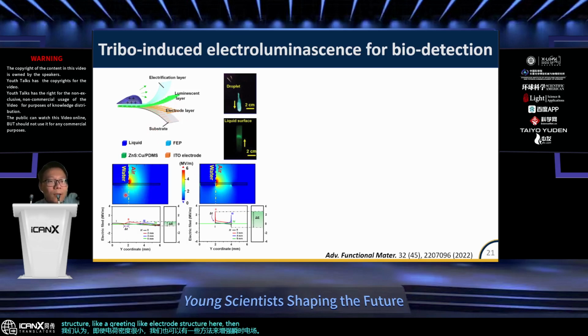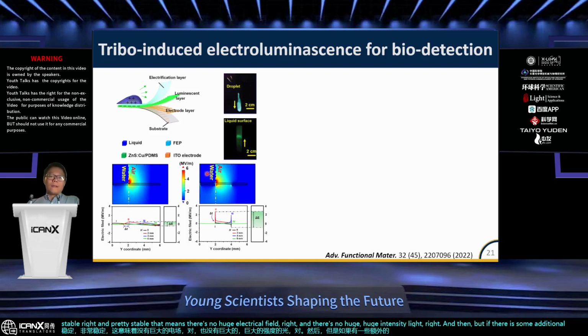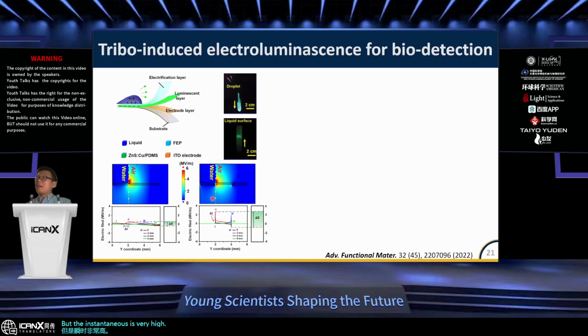Then we did some simulation. As you can see, when there are no grating electrodes, the electrical field change is actually pretty stable. And pretty stable means there's no huge electrical field, so there's no huge intensity light. But if there are some additional electrodes at the interface, when the water passes through the interface between the region with electrodes and the region without electrodes, the instantaneous electrical field becomes very high. And with this instantaneously high electrical field, we can actually generate enough electrical field to trigger the light.